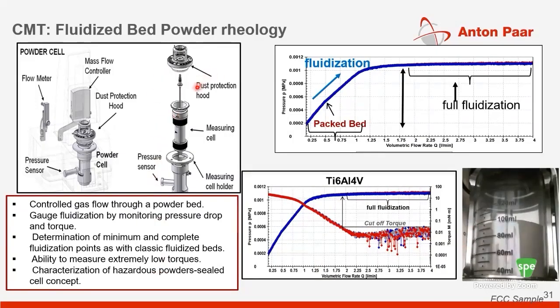And coupling it to an air bearing rheometer really helps to characterize very, very low torques. If you look at most powder devices which people use in the industry, they are mostly mechanical bearing devices. So having a powder rheometer on an air bearing device really opens up new experimentation when it comes to characterizing materials at really low torques, which is very important when you do fluidization type experiments. Also, you can see this dust protection hood here, which gives you a completely sealed system, and this allows characterization of hazardous powders. Since it's completely sealed, you can put it in a glove box or a hood, and study hazardous powders as well.